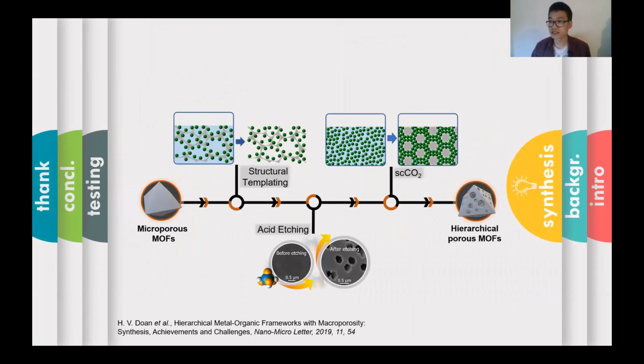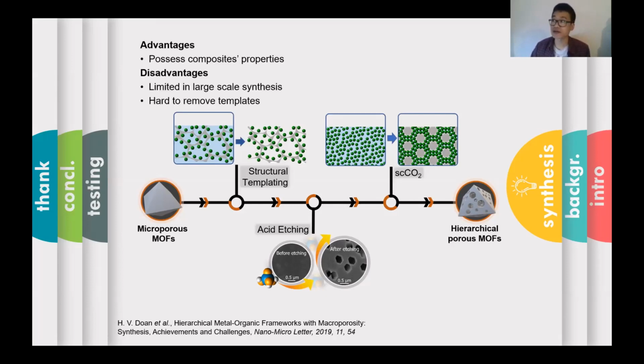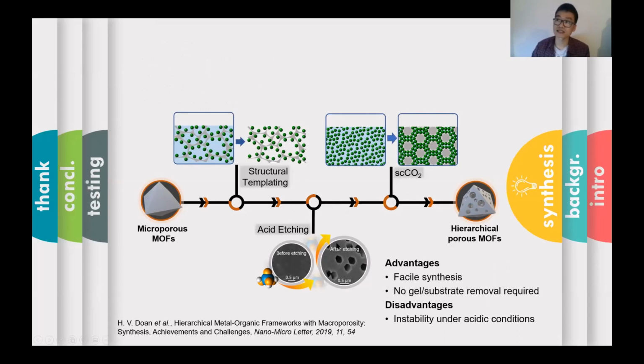Macroporous MOFs can be synthesized by different methods. Some of the commonly used methods are structural templating, acid etching, and the use of CO2. In the first method, MOF was formed around a macropore template to obtain composite materials. In this method, it's very difficult to remove the template after the synthesis without the collapse of the pore structures. And macroporous MOFs can also be synthesized by acid etching methods. These methods normally result in defect formation and can be performed without a complicated synthetic process. However, we need to be very careful because some MOFs are very unstable in acidic conditions.